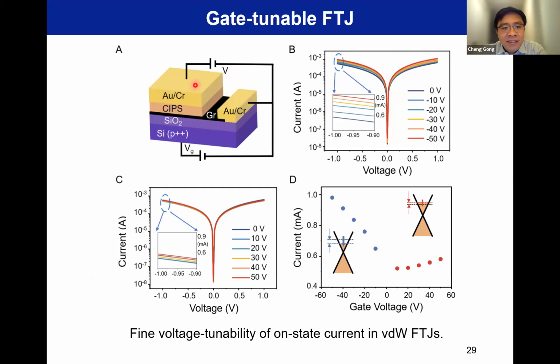Another small add-on: you have such a ferroelectric tunnel junction, and the graphene is already on a silicon oxide/silicon chip. So naturally, we can think about doing an experiment that uses a backgate voltage to tune the energy levels of graphene. You cannot control by 10 times simply by working on graphene, but you can fine-control the on-state current in an asymmetrical way, because the graphene's initial doping level is not intrinsic, it's not at the Dirac point. So depending on whether it is initially N-type or P-type doped, you have an asymmetrical V-shape control of the on-state current. So this is very interesting.